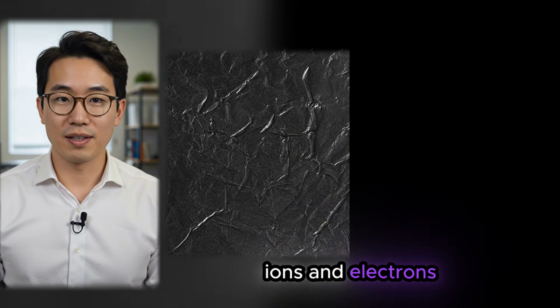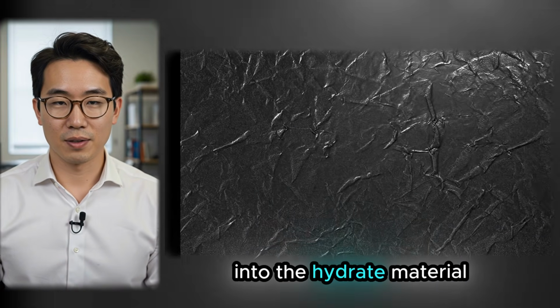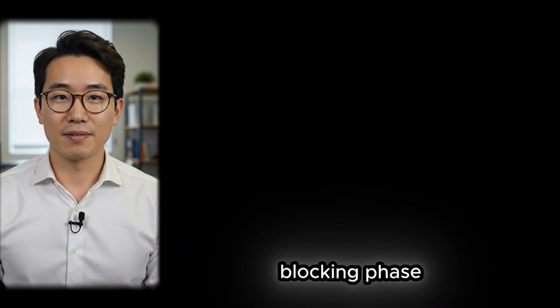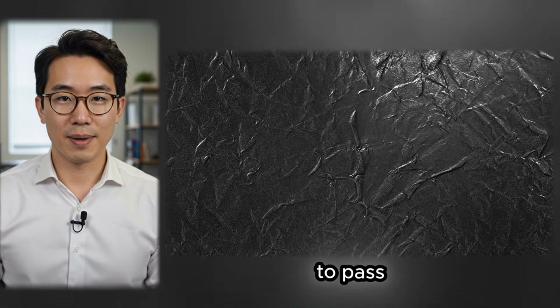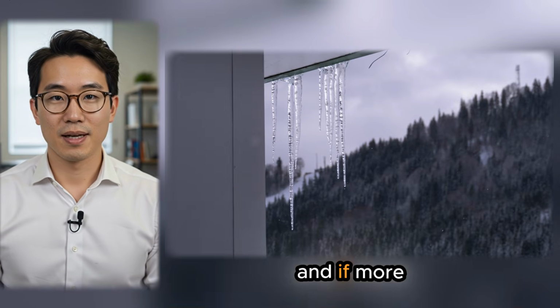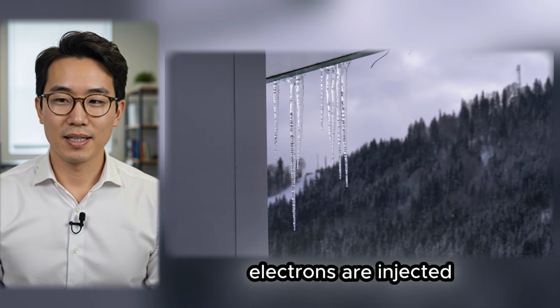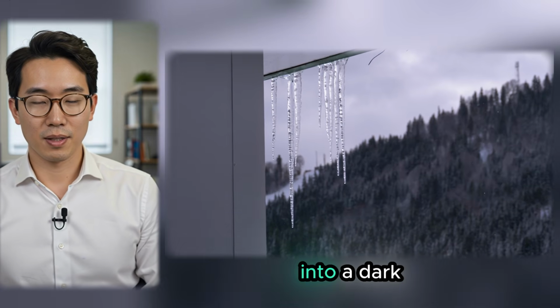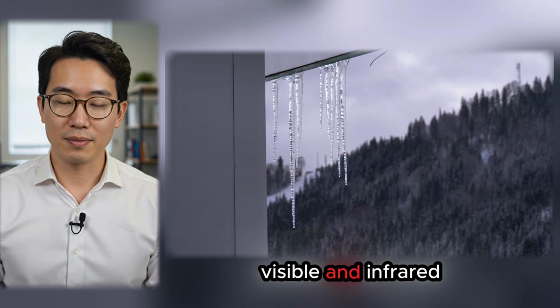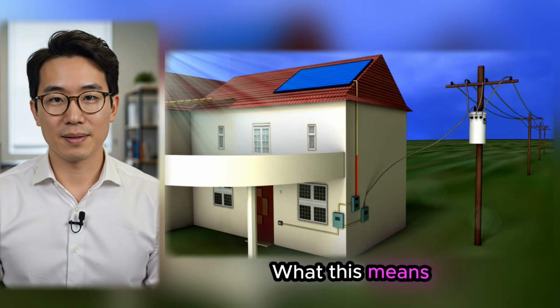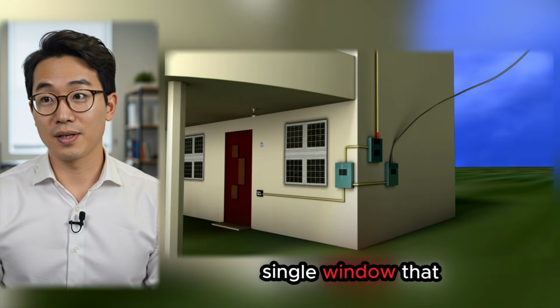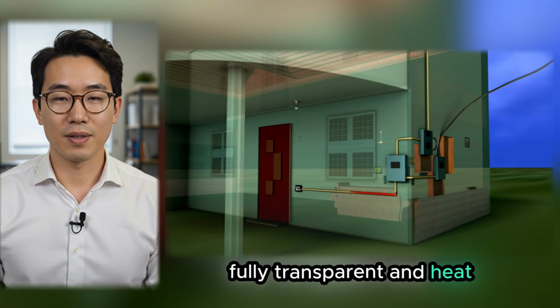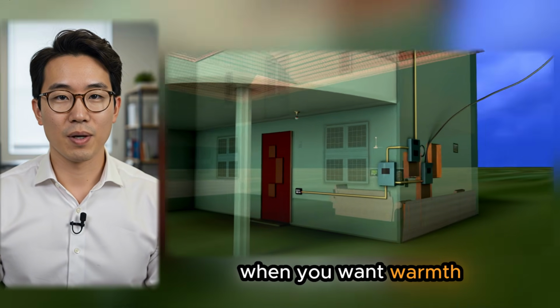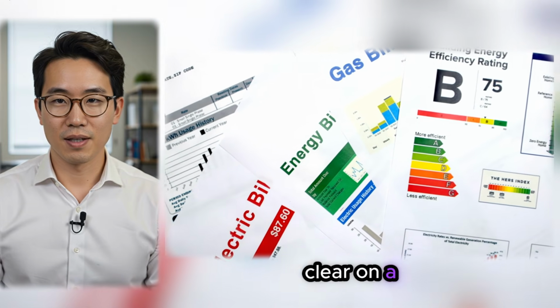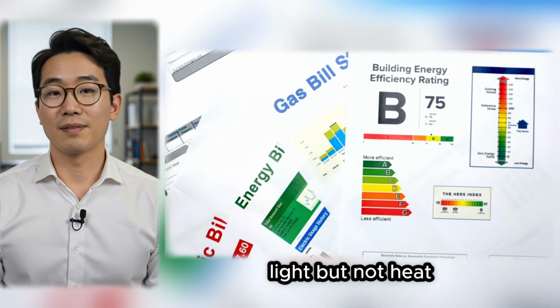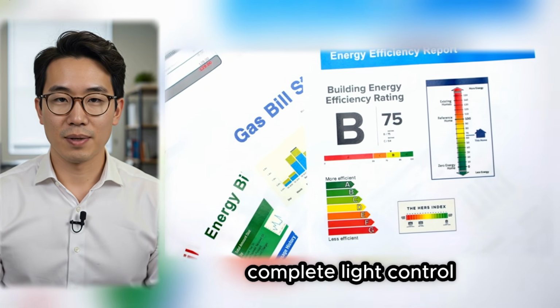And when lithium ions and electrons are injected into the hydride material, it first transitions into a heat-blocking phase, allowing visible wavelengths of light to pass through but blocking infrared light. And if more lithium ions and electrons are injected, the material then transitions into a dark phase blocking both visible and infrared wavelengths of light. What this means in practical terms is a single window that can be in any of three states: fully transparent and heat emitting on a winter morning when you want warmth, heat blocking but still clear on a summer afternoon when you want light but not heat, and fully darkened when you want privacy or complete light control.